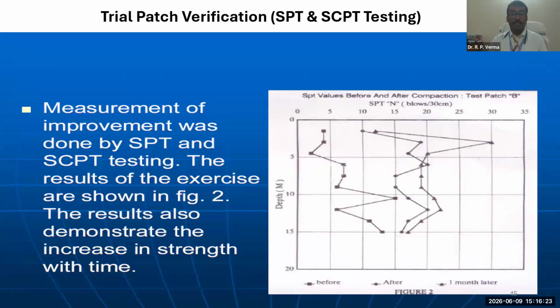How did they measure success? They used standard field verification methods: standard penetration testing and cone penetration testing. Let us look at the figure which maps the SPT N value against depth for test patch B. The curve with the square mark shows the baseline condition before compaction, where N values barely scratch past 5 blows per 30 centimeters in the upper zone. Following dynamic compaction, denoted by the triangular mark, you can see an immediate spike in soil resistance.